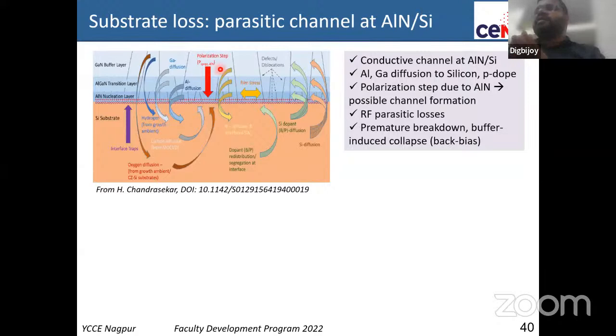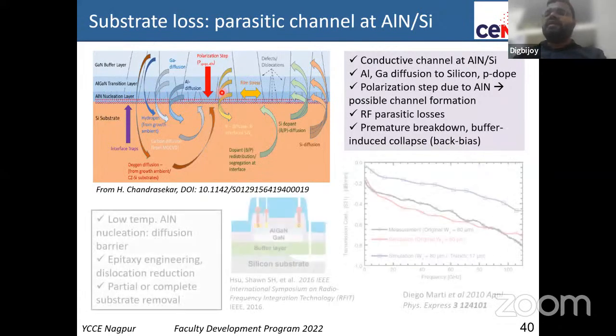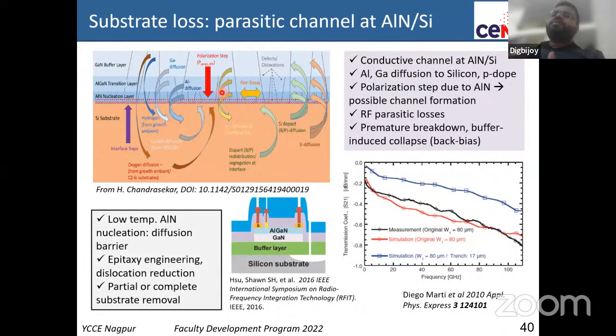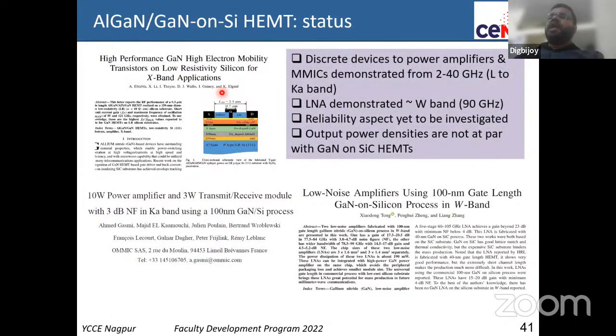So one has to really understand the interface and the material growth, so that all this out-diffusion and in-diffusion of these different species like carbon, hydrogen, oxygen, nitrogen has to be minimized. How can you grow the layer very insulating with lower and lower dislocation density, etc.? These are very important aspects. I'll not go into much detail of this. People in the industry, along with academia, have been working a lot on fixing these issues so that you can grow gallium nitride on silicon for microwave power amplification purposes. Now people have even been showing circuits and amplifiers at very high frequencies like 40 gigahertz, even 100 gigahertz.